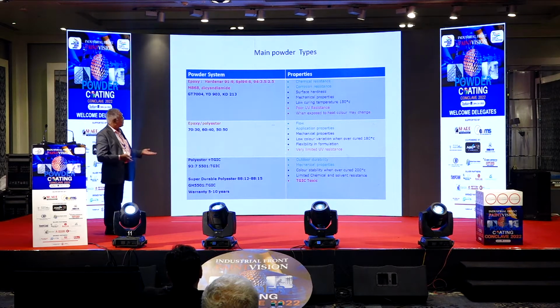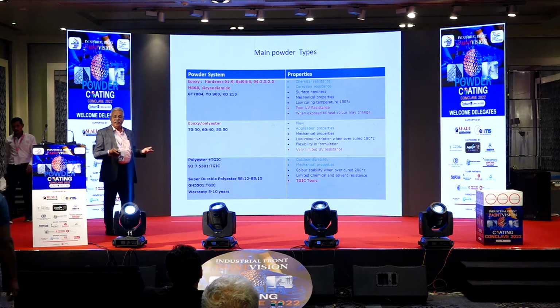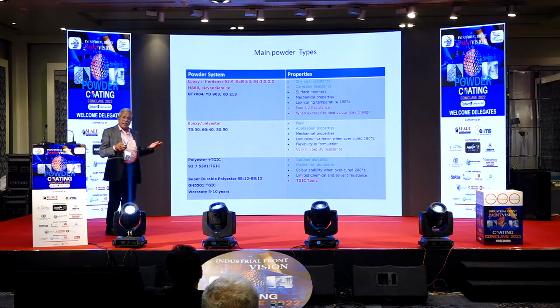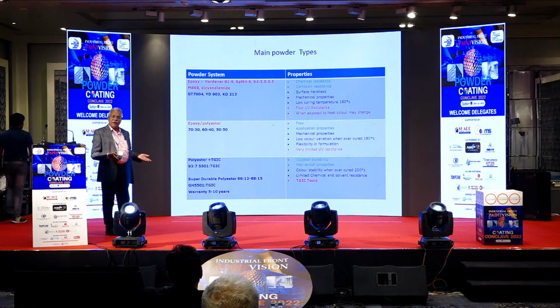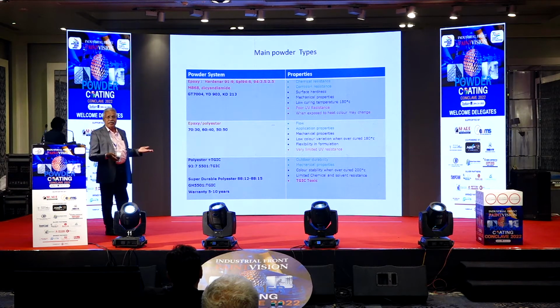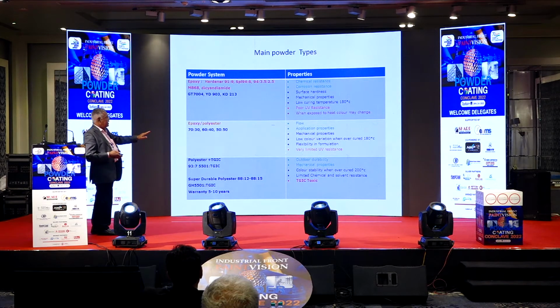But what is actually the lowest? This one is poor in UV. You all know that all types of epoxy, including liquid epoxy, you cannot use alone for exterior. You have to use it as a primer coat, and then the top coat will be something else. Then only will you get the UV stability. So that is why it is poor in UV resistance.